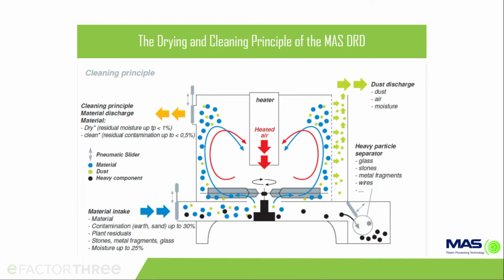This is the principle of this technology. It's a batch-fed continuous process. So flakes of material go into this centrifuge from a buffer silo. The blue represents the plastic, the black represents heavy contaminants like small pieces of metal or glass that we have not captured beforehand. And the greenish particles represent the moisture and the dirt that's in the material. The unit pulls this material into the centrifuge and holds it in a turbulent environment inside this machine. And we have heated air going in at about 100 degrees F, so it's not really hot, it's warm air.